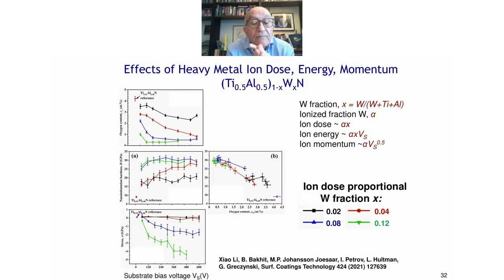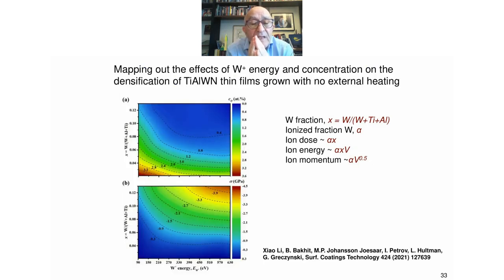The bottom panel shows the stresses in the films. So with having high dose and high energy, we actually introduce quite a lot of stresses. So there has to be an optimum here between dose and energy. So let's look at the next slide. All of this data here is mapped.